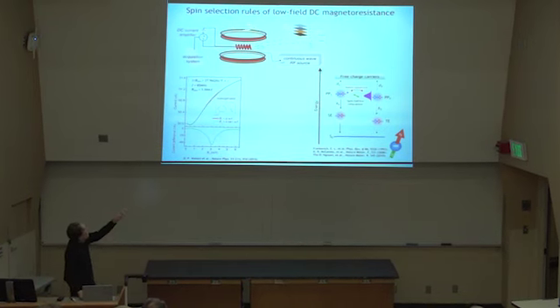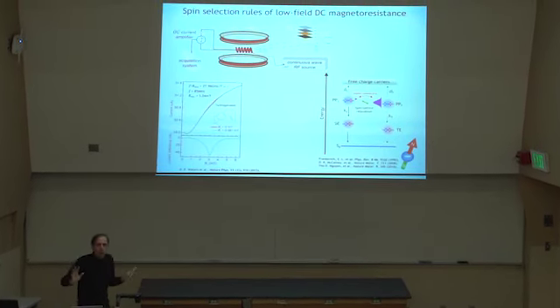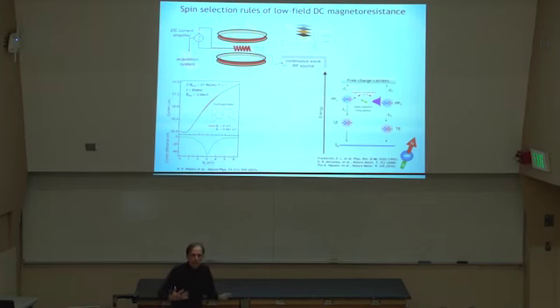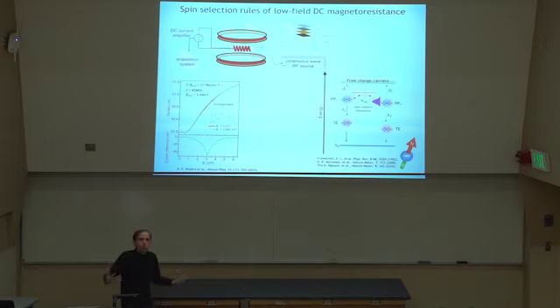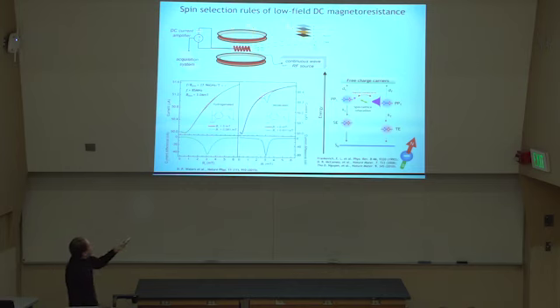How can I test this? I repeat the whole experiment, except with the same molecule and the same compound and the same device structure, the so-called MEH-PPV. However, I substitute all the hydrogen by deuterium. So I have smaller local magnetic fields, and all of a sudden my signal gets stronger and the line gets more narrow. And so that's kind of the ultimate proof that essentially the story that I explained here really works. And now, of course, you see we have about 1/6 of the change that magnetoresistance produces here. So this works really well.